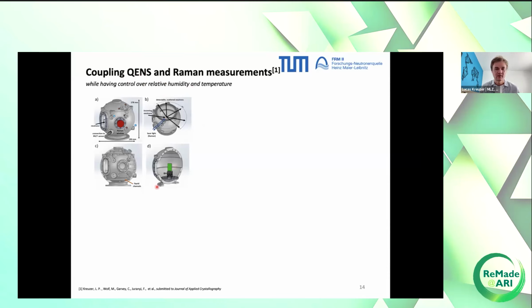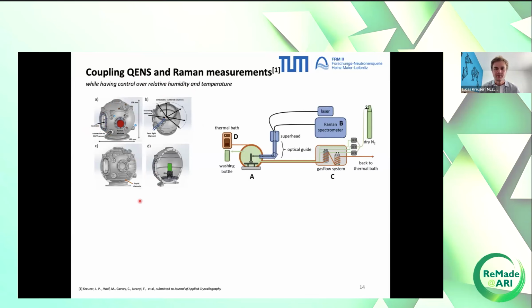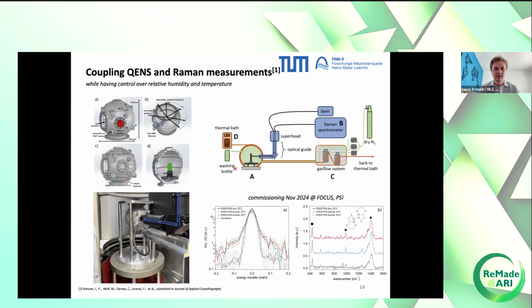And we built such a setup recently, where we have this humidity chamber. So we have control over humidity and also temperature. Neutrons would enter here. We have a Raman window for Raman measurements. The entire setup would look like this. We have here a connection to a thermal bath for temperature control, and a connection to a gas flow system which guides nitrogen with a certain humidity through the chamber. The entire chamber looks like this. This was last November at PSI, where we commissioned the entire setup. These would be our QENS data. This would be the corresponding Raman measurements.